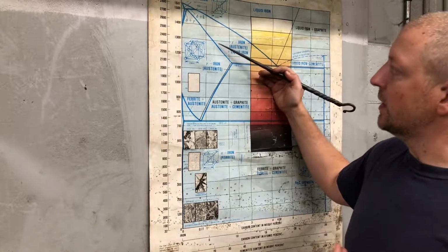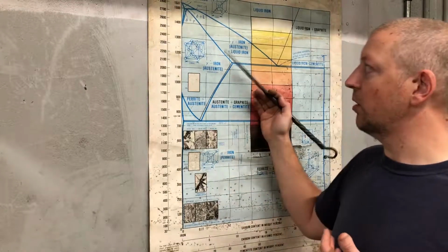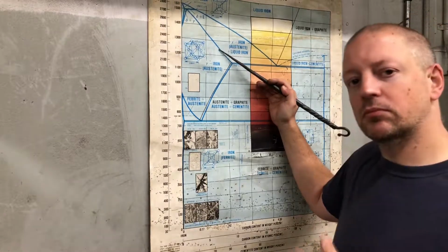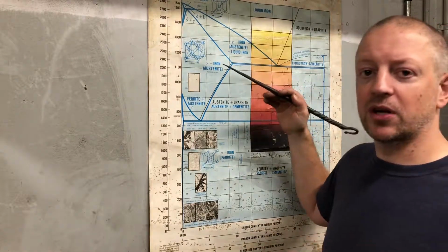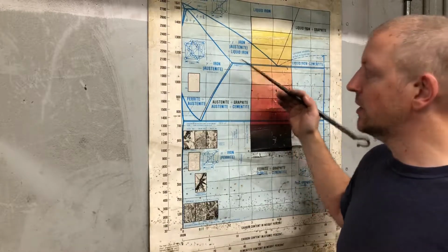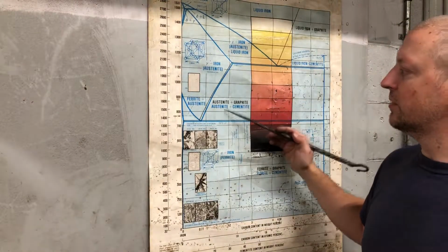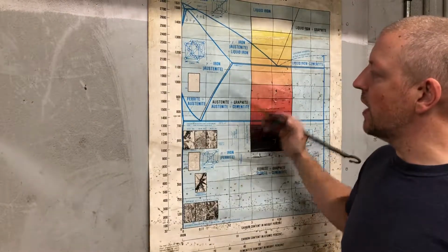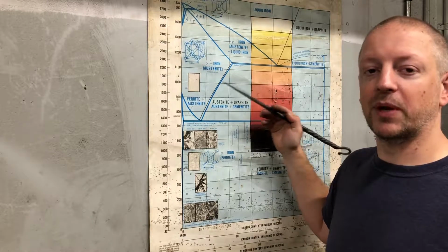So in the crucible steel that I make, I don't really have much in the way of phosphorus typically, so this is the line I need to worry about. Many of the antique wootz formulations, just because of the materials that they were using, did have some phosphorus, so they were more limited at the top end. But this bottom end line here, that transition from the austenite and cementite to the pure austenite, that line is kind of what one plays with in wootz to develop the carbide structures.